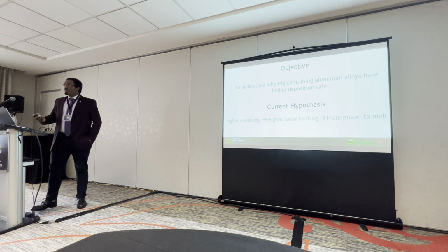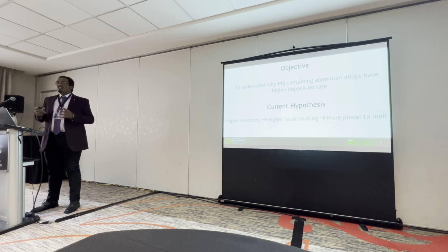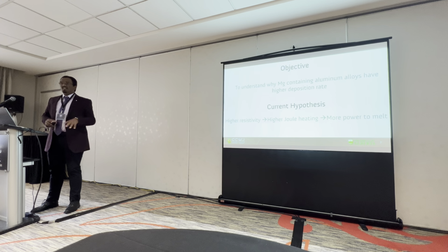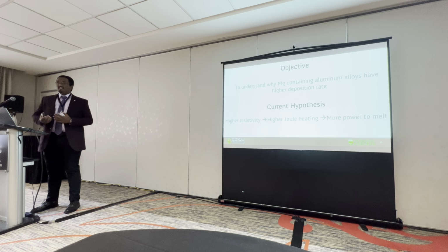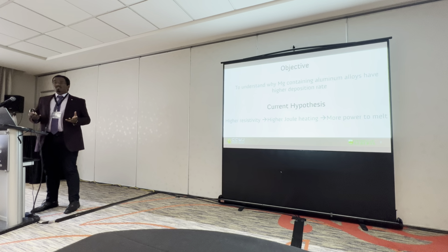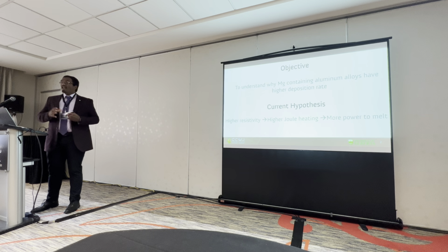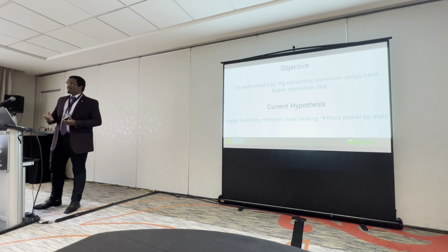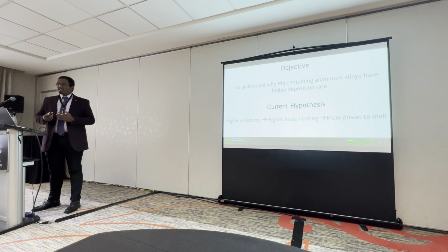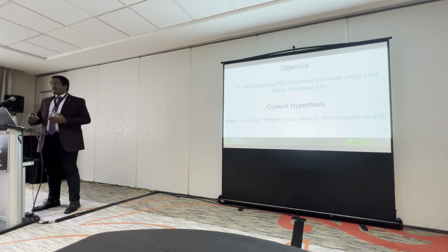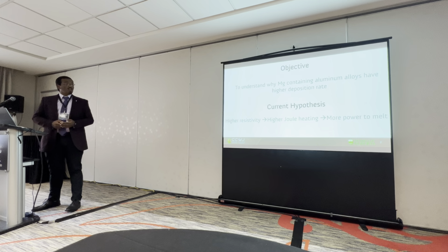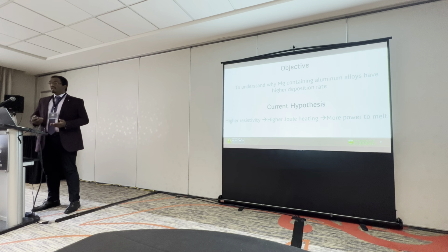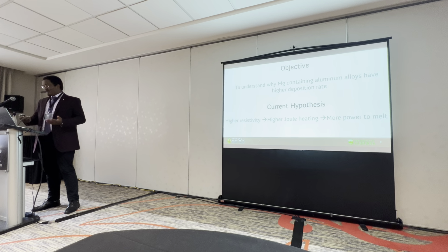The objective of what I'm trying to accomplish is to understand why aluminum alloys that contain magnesium in particular tend to have a higher deposition rate, and to understand the reason behind it. The current hypothesis is higher resistivity. Magnesium has a higher resistivity than aluminum, and aluminum alloys that contain magnesium tend to have a higher electrical resistivity. This will likely cause higher joule heating, which would provide the wire more power to melt easily, and this could be the reason behind the higher deposition rate. In my process, we are going to check if that is the scenario or not.